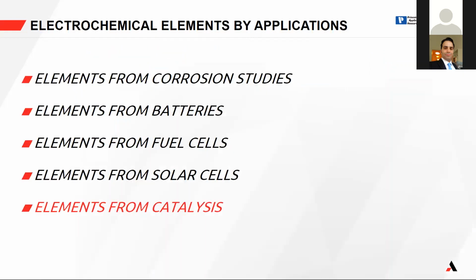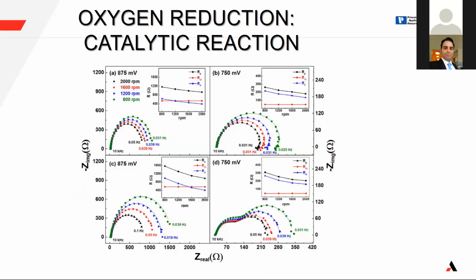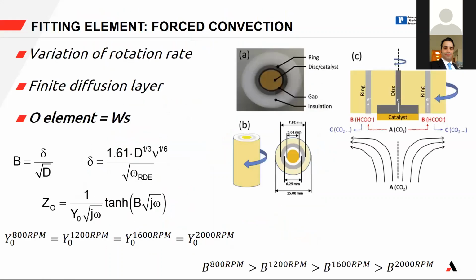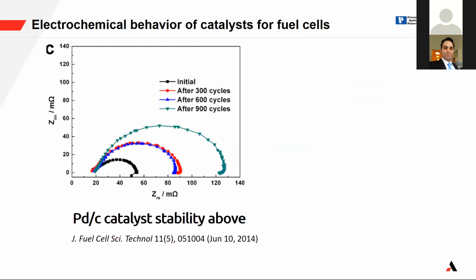Then in catalysis, the last element is in catalysis. I will be really fast. It is oxygen reduction. Sometimes you are using a hydrodynamic system or rotating disc electrodes, and in this case, due to the variation of rotation, you have this modification. You no longer have a linear diffusion like you expected, but you have a closed diffusion. So instead of being at 45 degrees, your diffusion is closing due to this hydrodynamic setup. So the faster you go, the closer your circle.